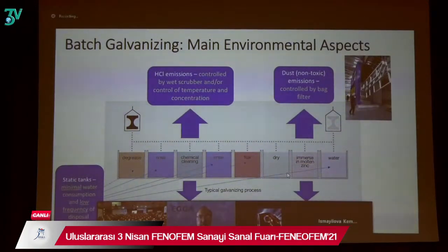So as you can see on the right-hand side of this slide, the galvanizing bath is almost always enclosed, and we can capture 95% of the fume from that tank and control that in a bag filter. We have some recyclables, zinc dross, which comes at the bottom of the bath when the iron and the zinc merge together, and the zinc ash, which is from the oxidation at the top of the tank, and those go to recycling. These are high-value zinc recyclables, and I'll explain a bit more about that in a moment.